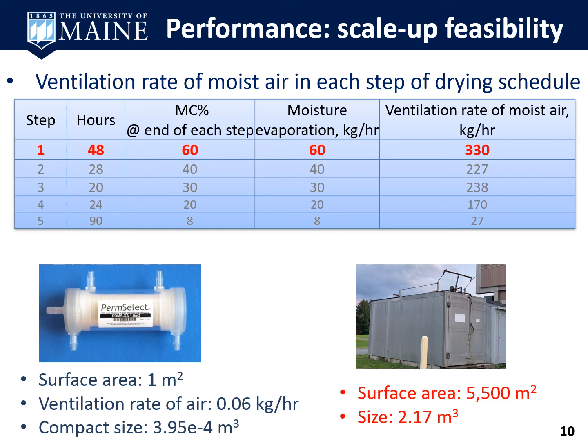Then we estimated the size of the PDMS membrane if we want to apply it in our small kiln. In step 1 of the drying schedule, the ventilation rate of moist air is the highest, which is 330 kilograms per hour. The small membrane module with 1 square meter surface area used in the lab test could separate about 0.06 kilogram air per hour. Therefore, processing the 330 kilograms of moist air means the membrane has a total surface area of 5,500 square meters. The size of the membrane is approximately 2.2 cubic meters.